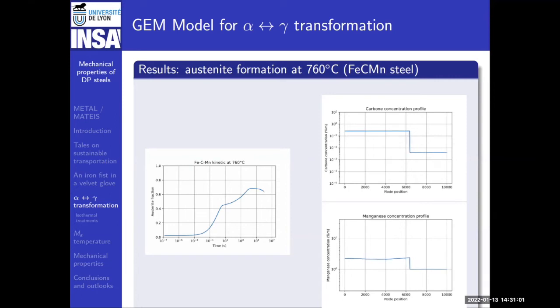Let's analyze what happens. During the first quite quick step here, you see that the carbon profile is building almost the equilibrium profile during this fast transformation. And while the carbon profile is building very fast, you see that the manganese profile is not evolving up to a given time where you start to have this high and low concentration in ferrite and austenite. Then at the end, the interface is here. It's going too fast for the profile to build up. Here, the manganese is diffusing, and then there is an equilibration of manganese within austenite. So this is what explains it: first, only carbon is moving, then manganese is moving in the ferrite, and then manganese is flattening in austenite. This is why you see this go back to the equilibrium.